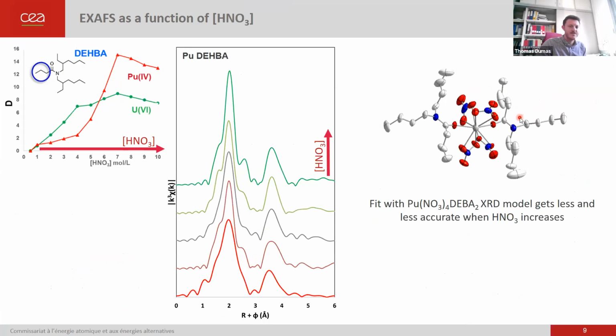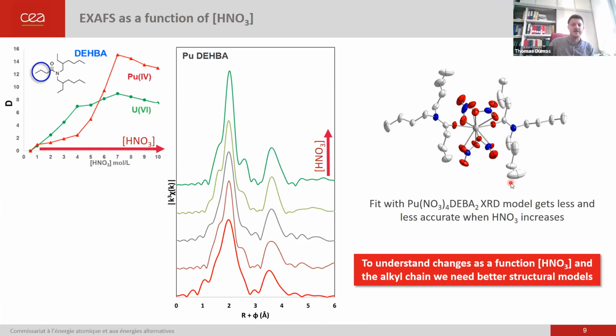Now, the second aspect I wanted to look at is that if you raise the acidity in the aqueous phase, okay, you are changing the extraction properties, and we keep the same extracting molecule here. And here is what you measure. You are measuring, okay, the same spectra for the lower acidity, and then by raising the acidity, you are going to be in trouble if you want to fit the data still with this tetranitrato inner sphere complex. Okay, so what we need now from that is another structural model to fit our EXAFS data, and this is where the calculation will come to our help.